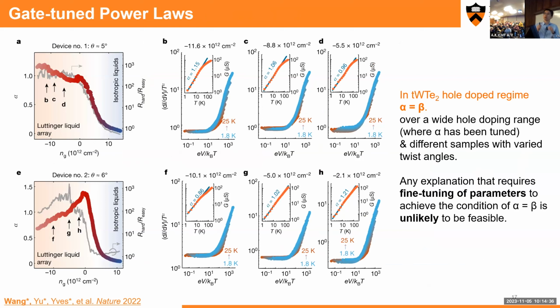But the question we don't understand very well now is that, for example, for the 5 degree and 6 degree samples, we cannot really go down to millikelvin. The reason is, as you can see here, the resistance already goes to a megaohm. For transport measurement, there's always a limit at a megaohm or 10 megaohm, and if we go lower, we cannot reliably measure the resistance. So comparing the alpha here and the alpha for 3 degrees is not easy, because the alpha from 3 degrees is at a temperature about 2 orders lower. I'm not sure it's fair to compare in this situation.